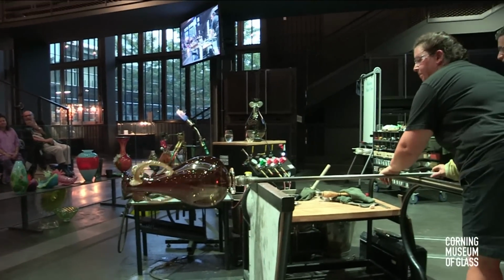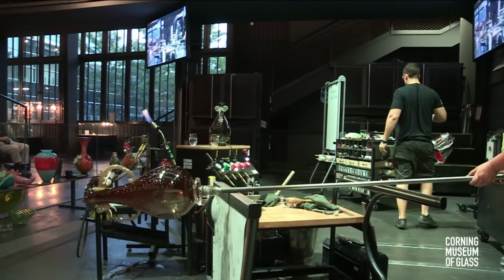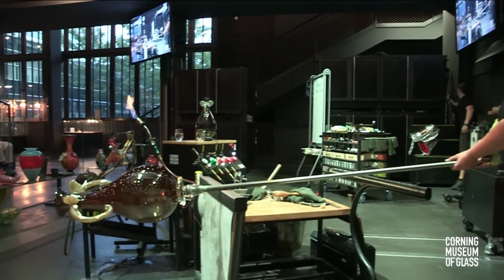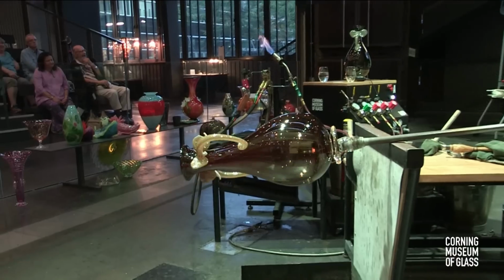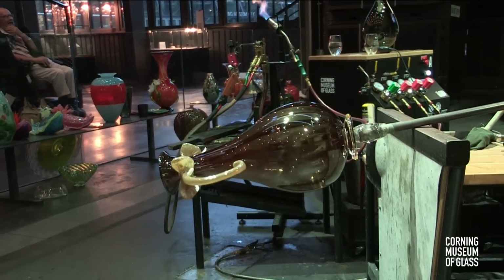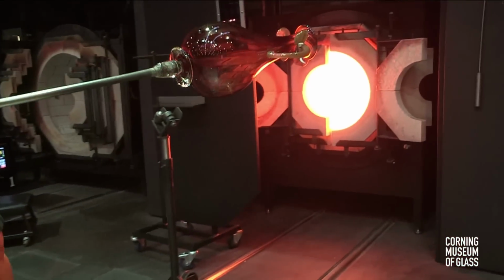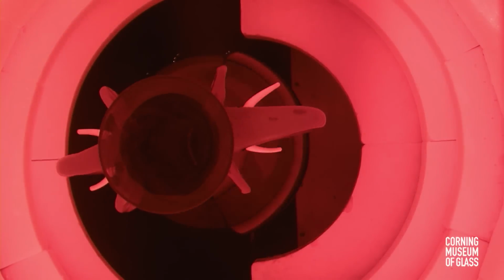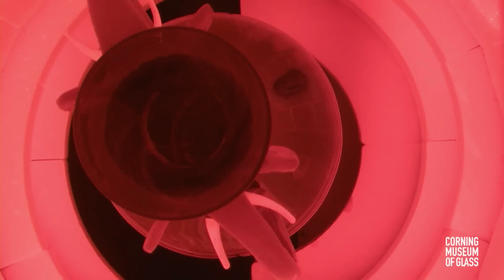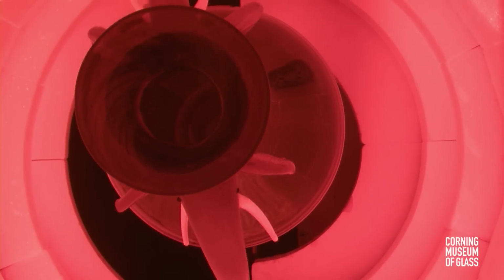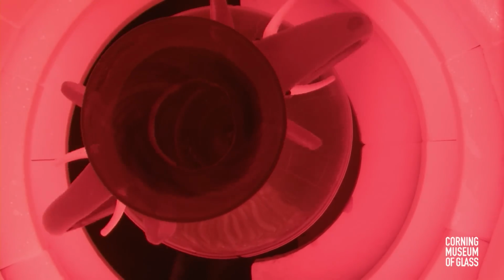We have 13 annealers here at Corning Museum of Glass. We will never run out of space to cool glass down. Now inside of our annealer, the glass is going to soak until it's all the same temperature. When it's all the same temperature, then the glass can drop down to about 200 degrees every 2 hours. It'll stop at certain strain points in the glass and soak there once again. This piece of glass is going to cool down over 12, maybe even longer, maybe 16 to 24 hours, just to make sure that the strain is all relieved.